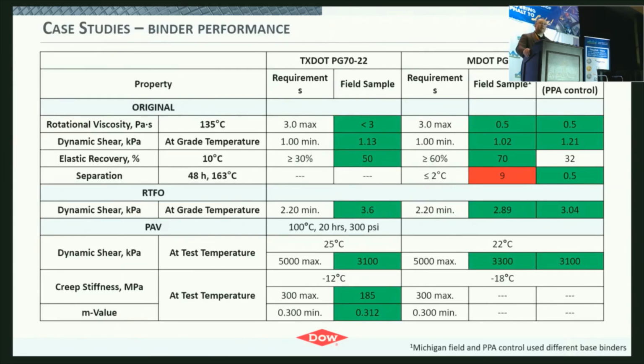This is the only data table I have, but what we've got here is, in the left series of columns, the TxDOT PG70 we targeted, and in the right column was the MDOT 64-22 we targeted. And so from a viscosity standpoint, we were well below the maximum for both materials. We passed the upper PG requirement, elastic recovery we passed, in both cases significantly higher than what the minimum was.